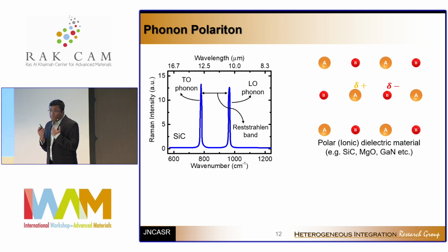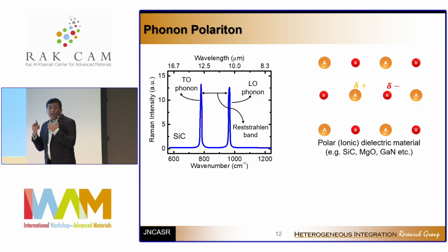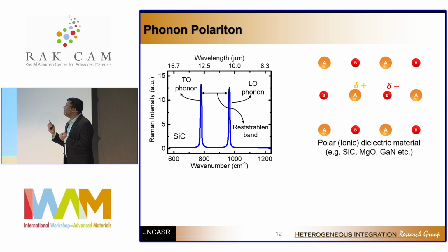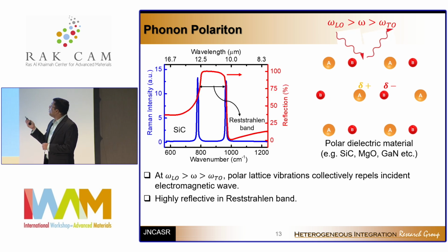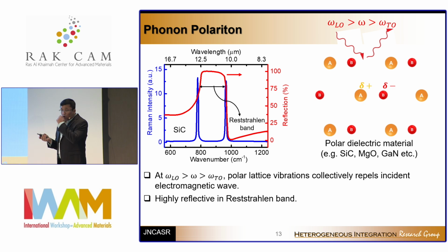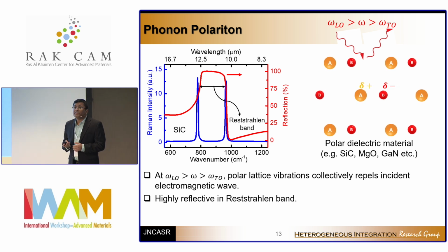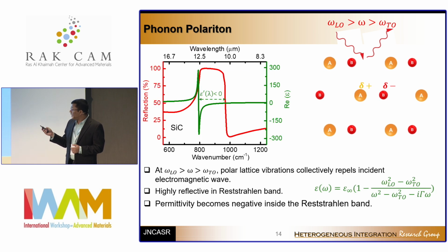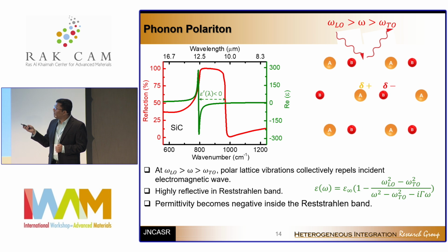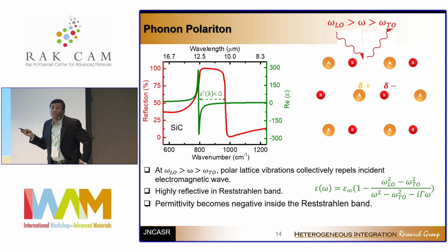Similar to Plasmon-Polariton, there is also another type of polariton. I'll just give a brief description of phonon-polaritons. If you have a polar dielectric medium, for example, magnesium oxide, silicon carbide, things like that, you have all this optical phonon vibration. And because it's a polar dielectric, the electric field basically splits the LO and TO phonons. And in between the LO and TO phonons, there is again a highly reflecting region, which is known as the Reststrahlen band. So it is a dielectric, right?